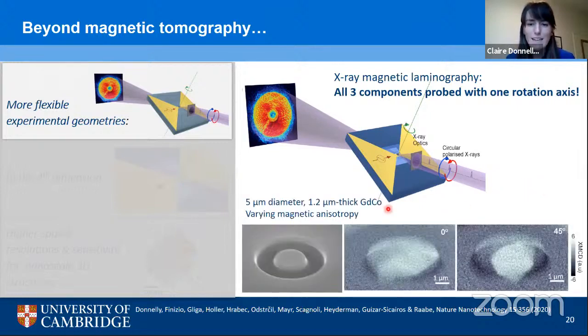And the sample that we looked at in this case was a 1.2 micrometer thick gadolinium cobalt film on a membrane that we milled a disc into. And I just want to mention that this film has a varying magnetic anisotropy. So when we look at these 2D images, first of all, we see, great again, the sample is magnetic. So we have these bright and dark regions corresponding to different directions of the magnetization. But we also see that the magnetization seems to be changing across the thickness of the sample. But of course, to see what's going on in 3D, we need to perform 3D imaging.